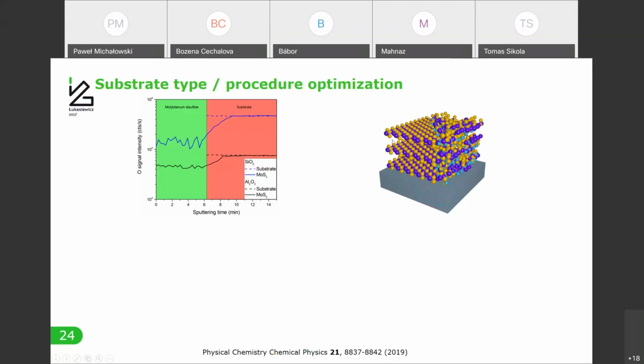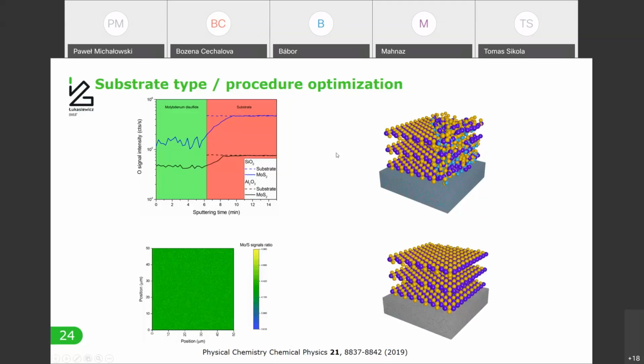So basically, that's why only a small part was a high quality film, where anything else was highly oxidized with an unknown stoichiometry. The solution to it was to either use a substrate which does not contain any oxygen, so we did it for boron nitride, or later on we simply optimized the procedure with the lower temperature process. And in both cases, we were able to obtain high quality material.